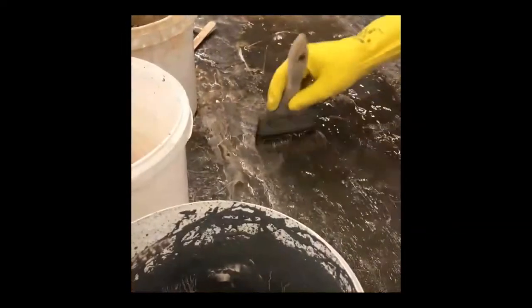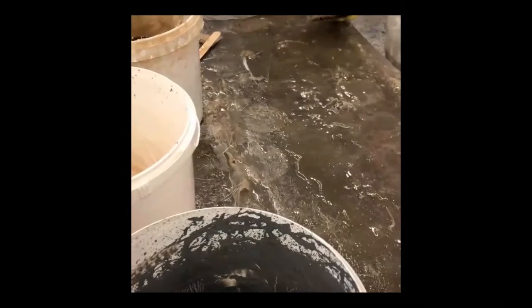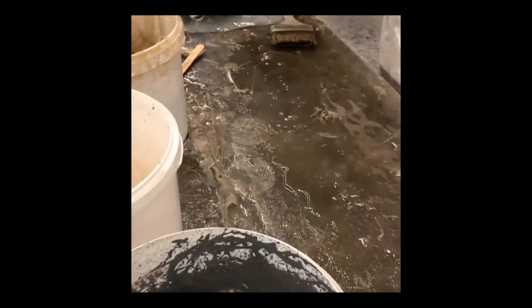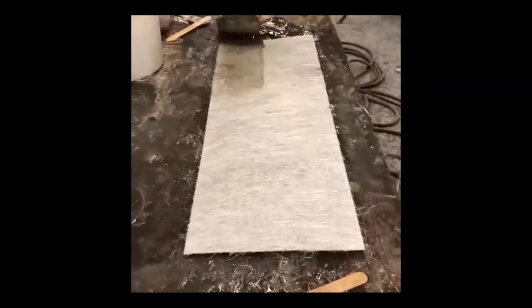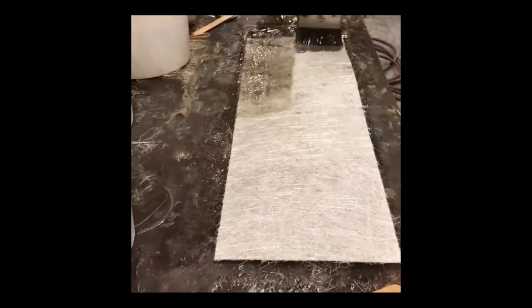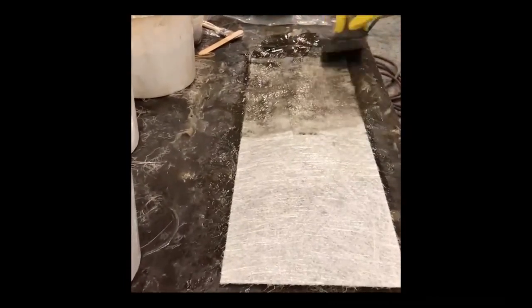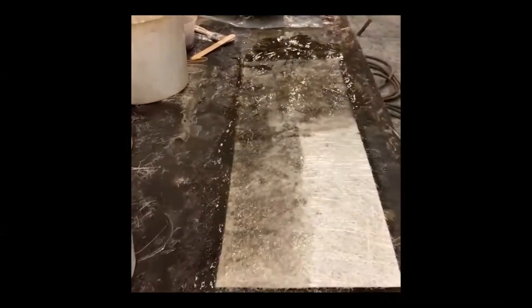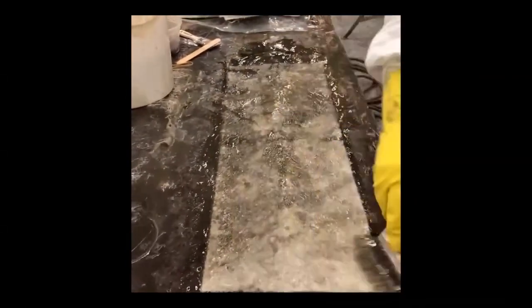So you can see he put some catalyzed resin on this surface here. You can see it's been well used. And he takes some of the glass reinforcement that comes from the kit and he saturates it with the catalyzed resin. And he's going to do that for up to five layers. Because remember I was saying you can only apply about five layers at a time. So the technician saturates that.